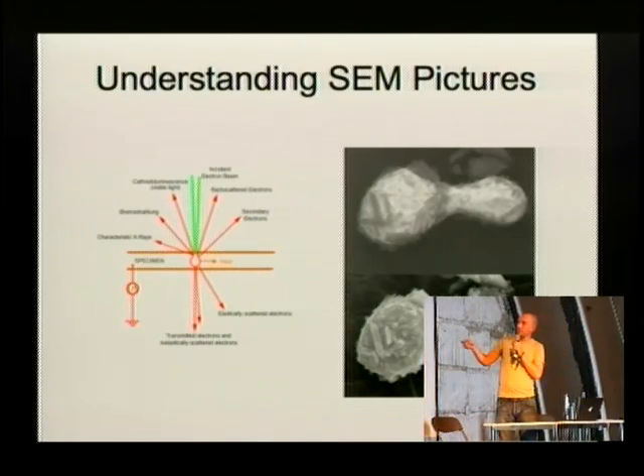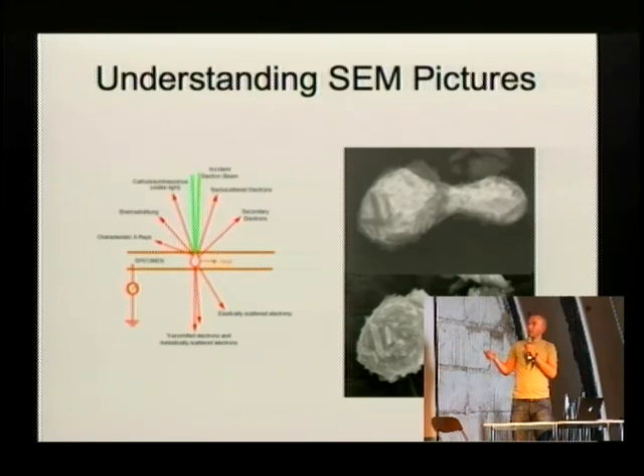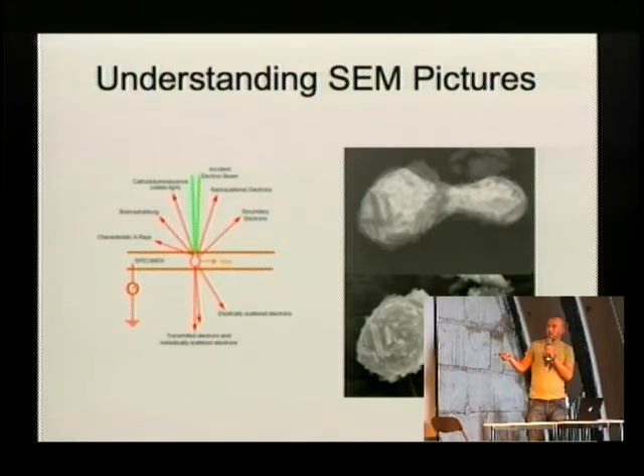If you look here, you have some incident beam of electrons that hits the sample at some point. It's very small, but unfortunately the electrons are not stopped immediately. They continue on and cause several different effects. I will not go into detail too much. You have light coming out, you have X-ray radiation, you have electrons. If you have a thin sample, you have electrons that just go through. Some go through without even noticing that there's a specimen, others get deflected. But for the scanning electron microscope, the interesting parts are backscattered electrons and secondary electrons.